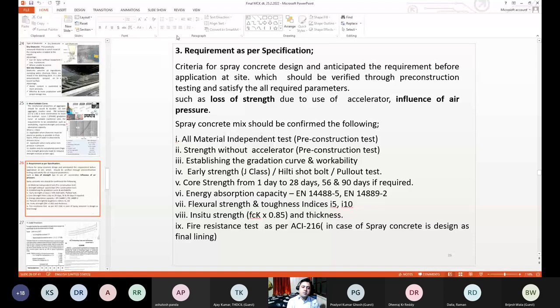In situ strength shall be 0.85 of the characteristic strength, and the fire resistance as per ACI 216, in case the spray concrete is designed as final lining, shall be done. So these are all essential parameters that should be considered. So I am now going on to codal provisions.